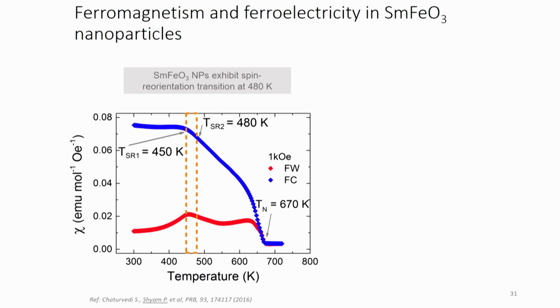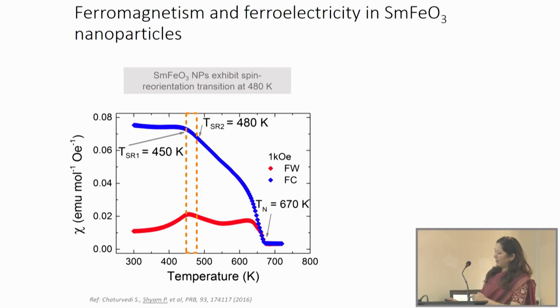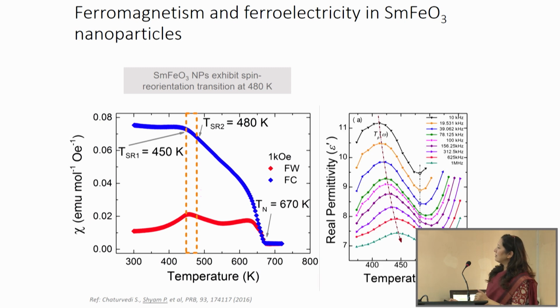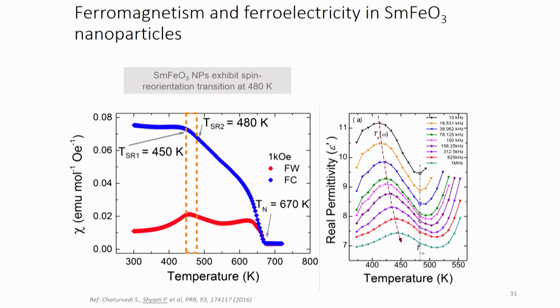Then we saw that there is a transition at 480, as you see here, 480 degree Kelvin. There is a transition which is a spin reorientation transition. So spins are reorienting at that transition. Then we also saw that permittivity has some changes at 480. So that means this is magnetic behavior, where spin reorientation is taking place at 480, and similarly here you see there is a sharp transition for the permittivity in terms of temperature at exactly the same temperature, 480.